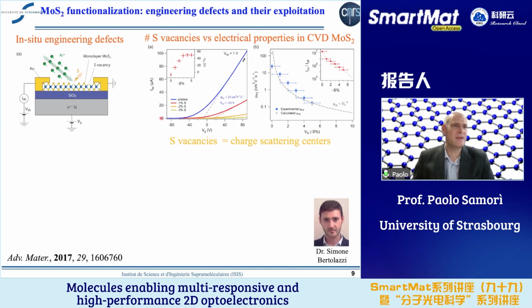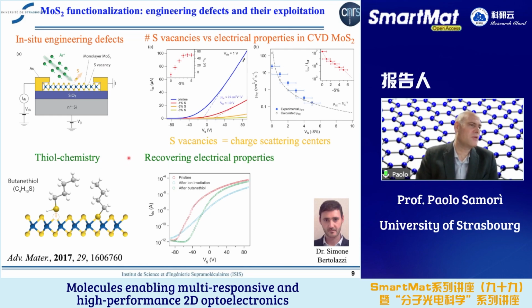Now, the idea is that these sulfur vacancies can actually be replaced, they can be filled, so they can be healed with thiol molecules, okay? So the thiol molecule fills the vacancy, heals the vacancy. And so what we have been doing in this study is we have been using a simple commercial butanethiol to, let's say, heal the sulfur vacancy in MoS2, and this is reflected by the fact that we have gained back, so we recuperated or recovered, the electrical characteristics of the pristine MoS2 to a great extent.